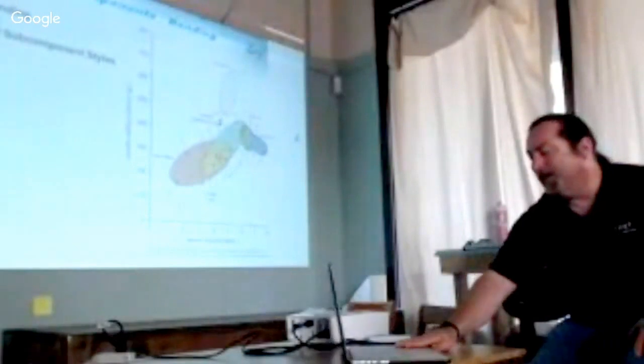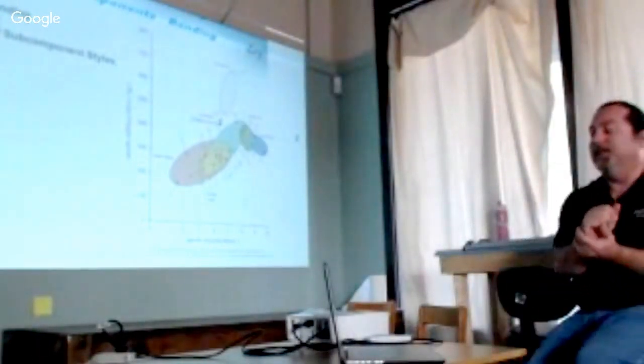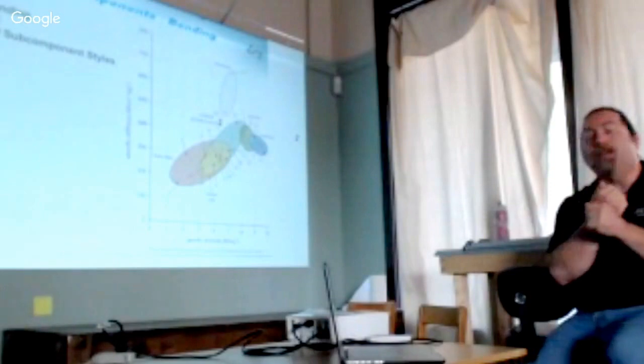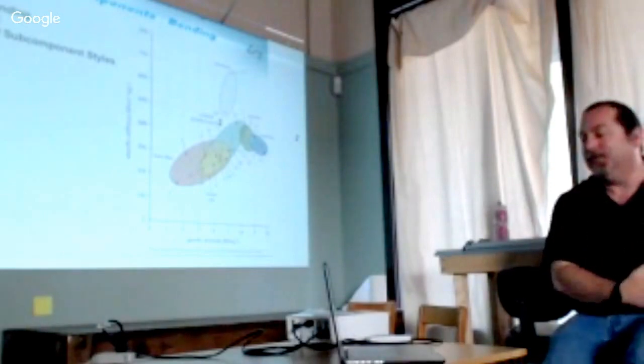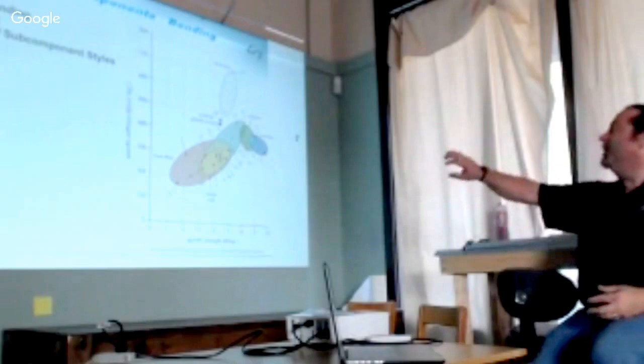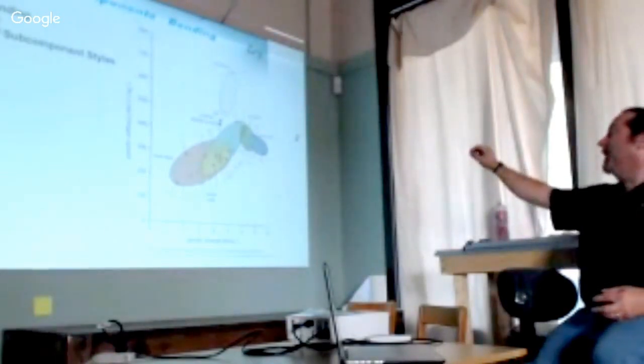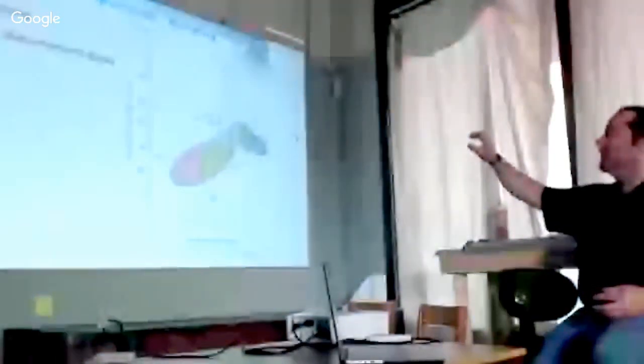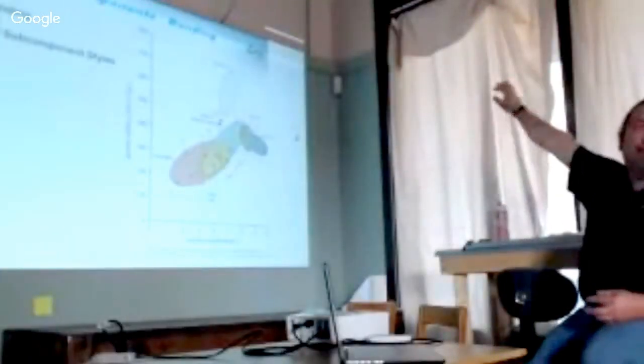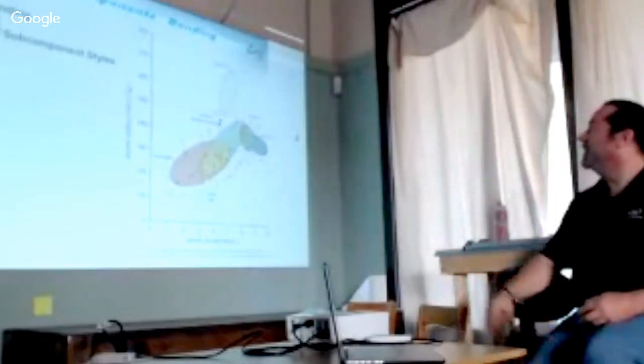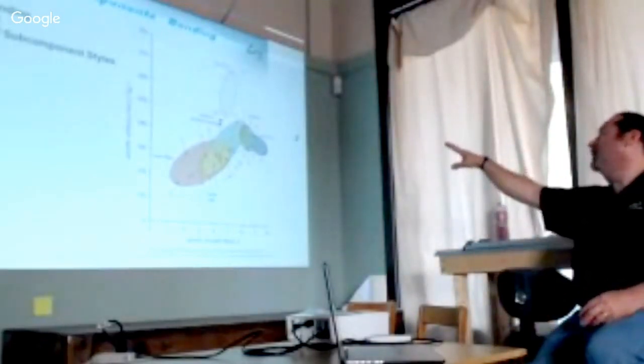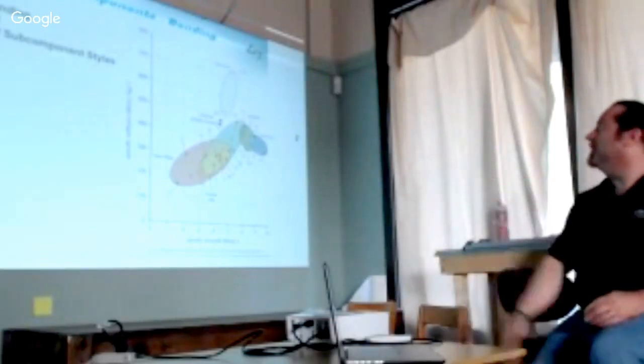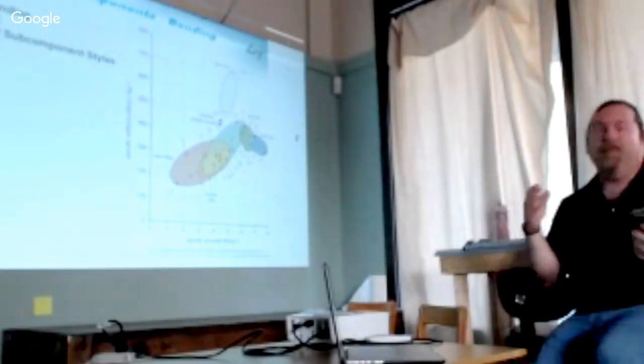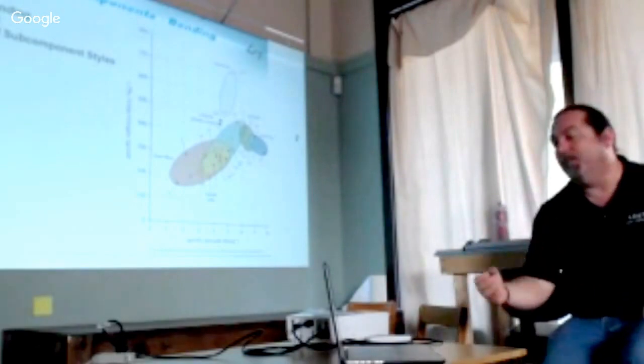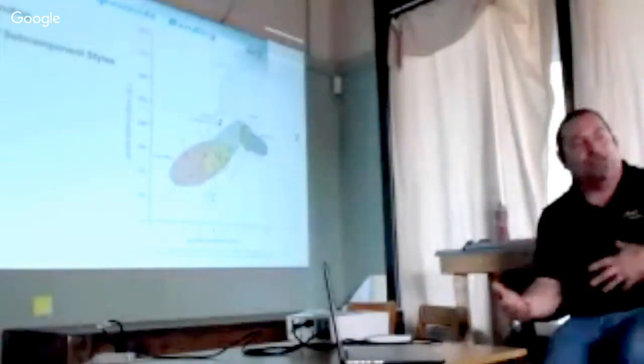And then we just wrote a paper for the American Society of Composites, and we produced this plot. It's an Ashby type plot. It's typically used for materials selection. We grouped the different types of boxes and showed specific stiffness as a function of specific strength, so that higher performance stuff is up to the upper right. The aluminum really performed really well. The overwrap boxes also performed well. What was really interesting was the different shapes, and what performed better in bending versus torsion.